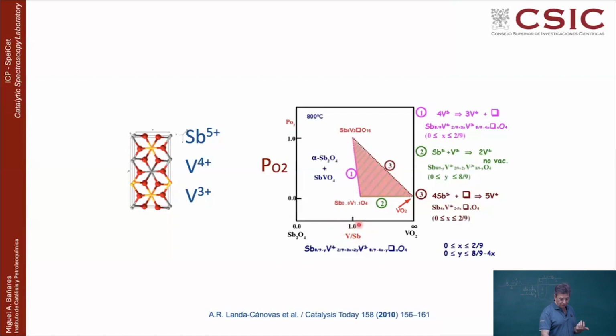So basically the vanadium antimony ratio, which is typically 1:1 in this system, VSbO4, as you decrease the partial pressure of oxygen, what happens is that you get an increasing excess of vanadium. That means that antimony is getting out of the lattice. And they observed those changes were very reversible. And that was telling you, okay, this system is extremely dynamic.